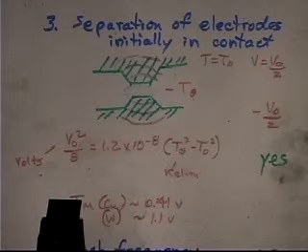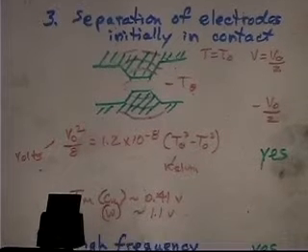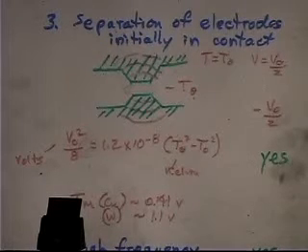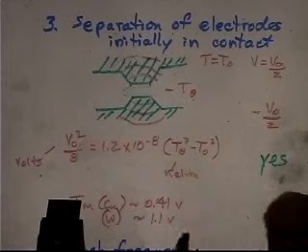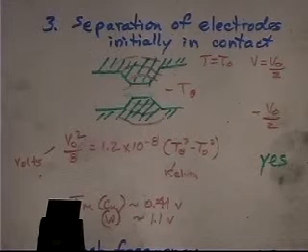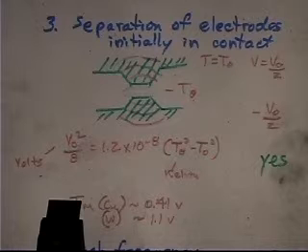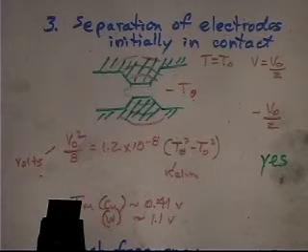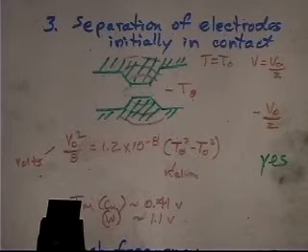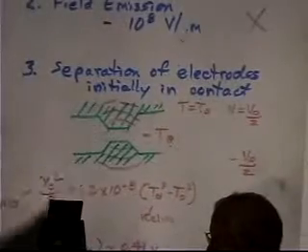So if I bring these two things together and pull them apart, the resistance has to go from some low value to an infinite value, and as it does that, it has to pass through some value that will essentially vaporize whatever the material is. Not only will it vaporize it, it'll heat it up, give it enough superheat, you'll ionize it, and as soon as you have some ionized gas and voltage across there, you strike an arc. So this is basically touch starting to initiate an arc. What we have here is that these two don't initiate welding arcs, these two do.